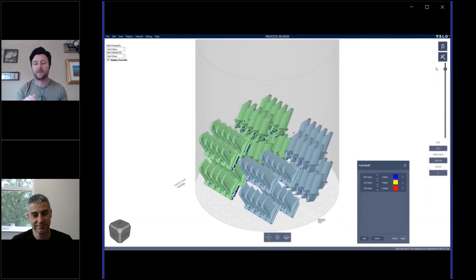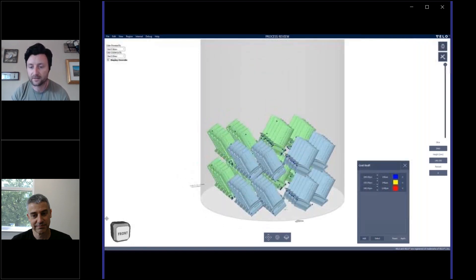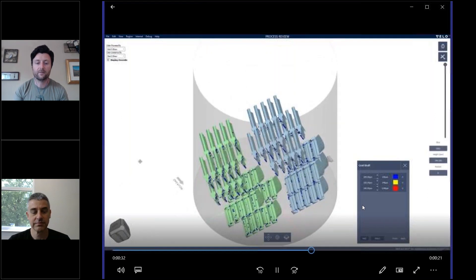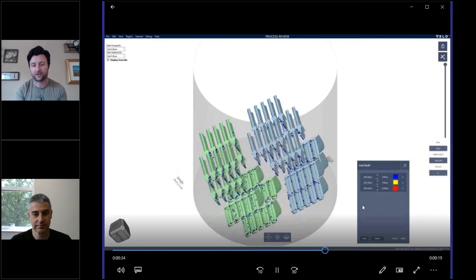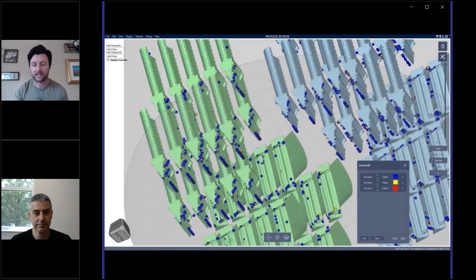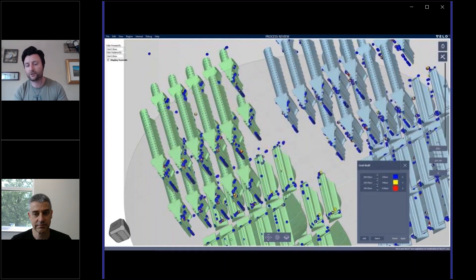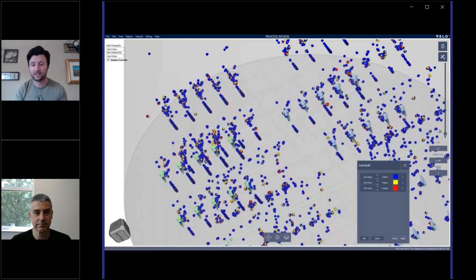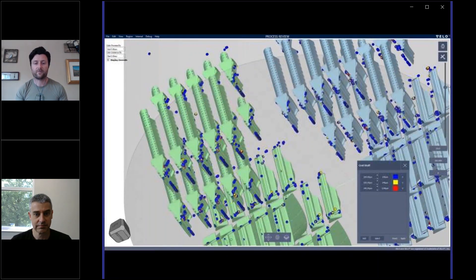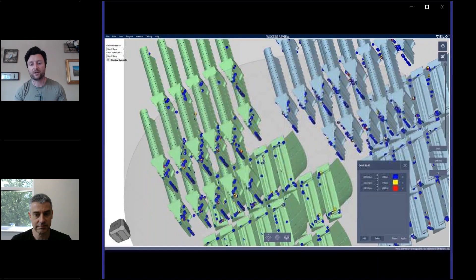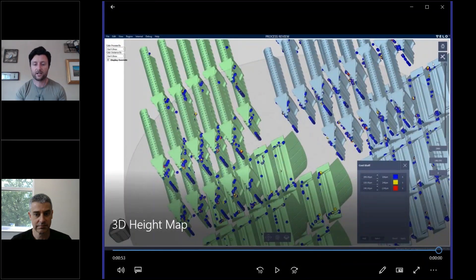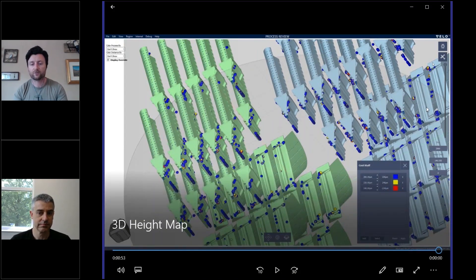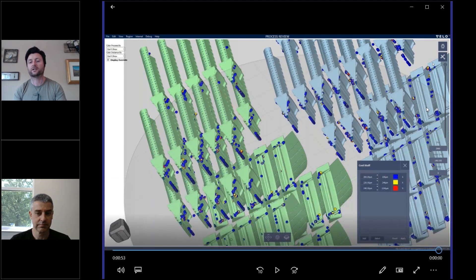So blue is a minor protrusion, yellow gets a little bit more serious and red is above 240 microns is what we have here in the legend. One interesting thing you can see, the leading edge or the bottom edge of the part is actually kind of a blue line. And that's because it's slightly protruding as you're building this free floating part. There's nothing to constrain it. And that's fine. That's actually what you would expect from our system with the ability to print free floating. But you are able to take all of this data through the entire print and then project it back onto the CAD and onto the actual parts so that you can see where these different behaviors are occurring.